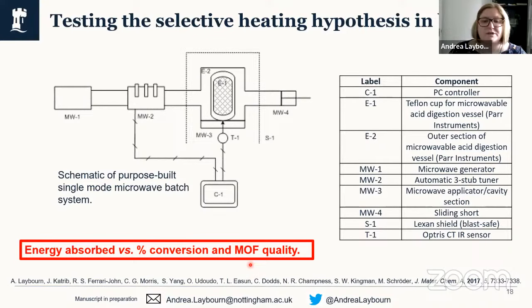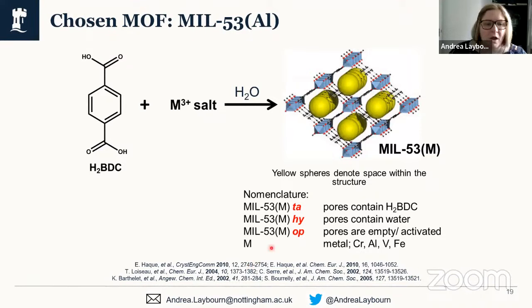So I'm now going to show you the results of this investigation. For our particular investigation, we wanted to focus on MIL-53 aluminium. This is a very archetypal MOF. There is a lot of literature available, and the mechanism for the formation of this MOF is well known, hence our choice. It is synthesized from the terephthalic acid linker, and you can react it with a range of metal 3+ salts. In our case, we used aluminium, and we synthesized this in water, in keeping with the sustainability drivers we have in mind. This forms the MIL-53 structure.